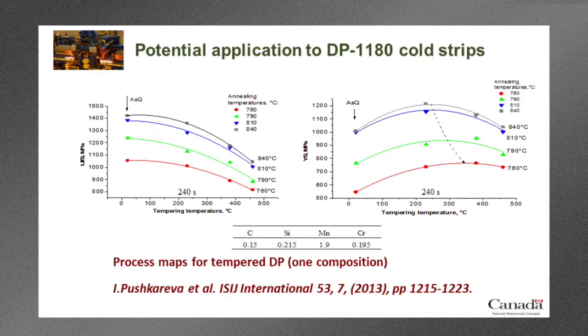If you look at the yield strength under the same conditions, the behavior is quite different. What you actually see is that the yield strength will increase with tempering temperature up to a certain maximum, and then it starts to decrease again. For steels where there's a lot of ferrite, that's due to static strain aging in the ferrite. But for steels up here where there is no ferrite, this is a strengthening effect of martensite with tempering. And that's actually not very well understood.